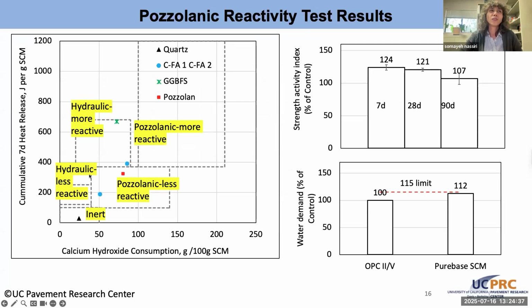What we really like to look at in this graph: we place a little bit of the material in an alkaline solution and see how much heat is released in isothermal calorimetry over 7 days, and that's what you see on the y-axis. And then we also take that paste out after 7 days, and we measure how much calcium hydroxide is consumed in that sample by thermogravimetric analysis. We plot the two together.